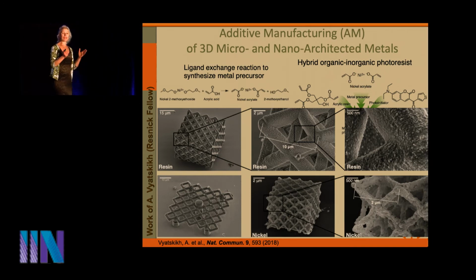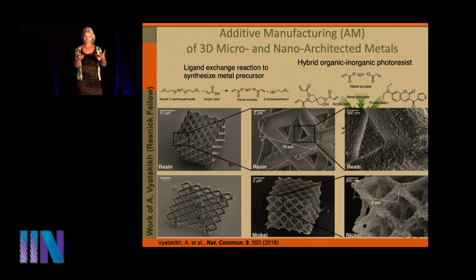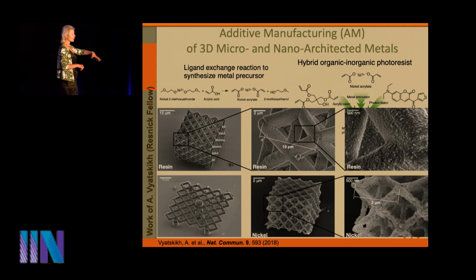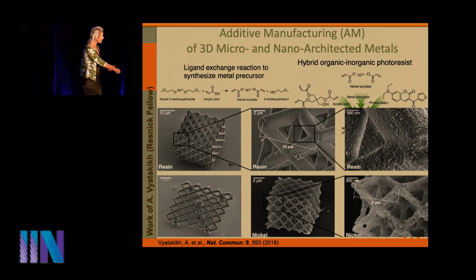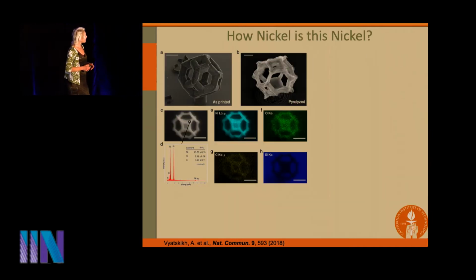Now, how do we get rid of the organics if what we're really interested in is nickel? Well, you burn them. So what we did is we pyrolyzed this structure, which is a fancy word for burning without oxygen. And when that happened, of course, a lot of the organic material volatilized, all of it did, and the concomitant shrinkage that came with this allowed the final additively manufactured structures to have a unit cell size of only 2 microns, but each individual beam here is about 400 nanometers. So my student Andre made these, and then the question, of course, was, well, all right, how nickel is this nickel? You say it's nickel, but is it really nickel? It's all chemically derived, it's new.